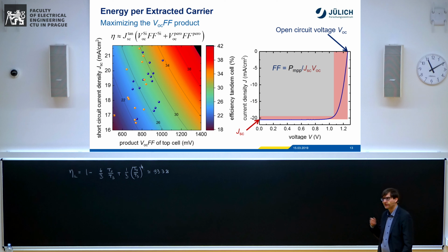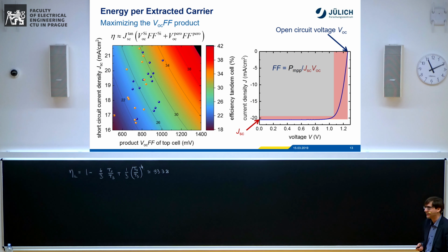Yeah, we tried it, of course, and it totally doesn't work yet, because we can't keep the 20 milliamps, not even close. And we have lots and lots of technical problems getting there. But it's an interesting estimate of where you could go, and by now we've also tried to increase the band gap a bit, add some bromine, and then we can go up with this product to 1.1.